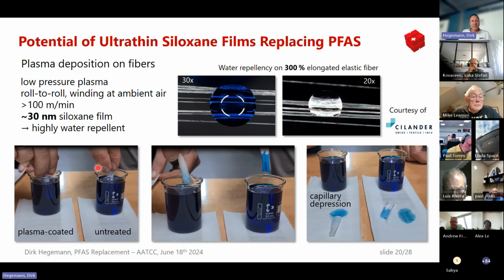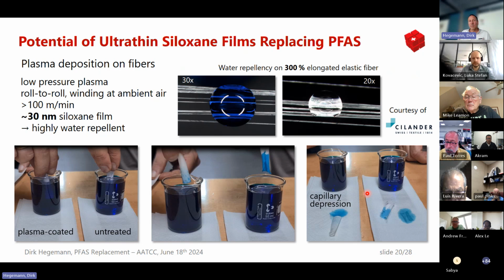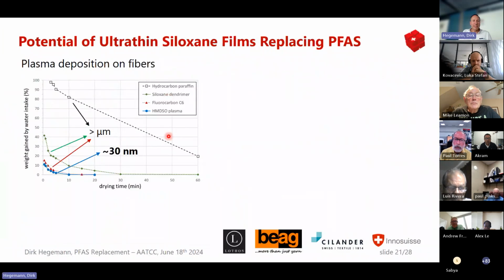And just to show the difference, the plasma coated, it's a knitwear, so it's an open structure. It takes up water. This is just colored water here, but then it shows quick drying properties, while a reference sucks in the water and keeps the water in the textile structure. And even on an elastic fiber that has been elongated by 300%, we still maintain these very good hydrophobic properties. When it comes to the comparison, we were immersing it into water for 10 minutes and then removing it, measuring the weight gain and then the drying properties.